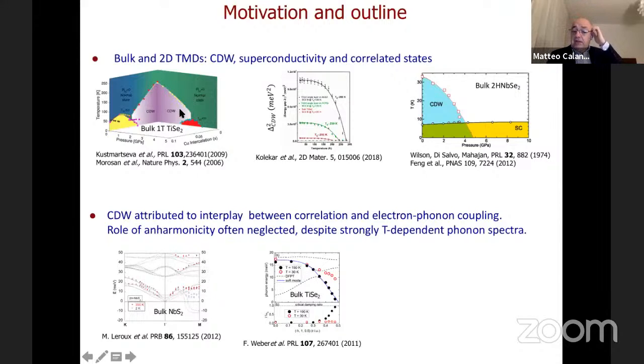Now, first of all, I would like to tell you that in single layer form, there are several reports of superconductivity, not in titanium diselenide, but for example in niobium diselenide, but the TC is not uniform between different reports and changes substantially. So probably single layers are very dependent on environmental conditions, like substrate effects and so on, as far as the superconducting TC is concerned. On the contrary, if you look at the bulk, this is a very well established case, 2H niobium diselenide. Here you see that superconductivity has almost constant TC whether you are deeply inside the charge density wave or outside.